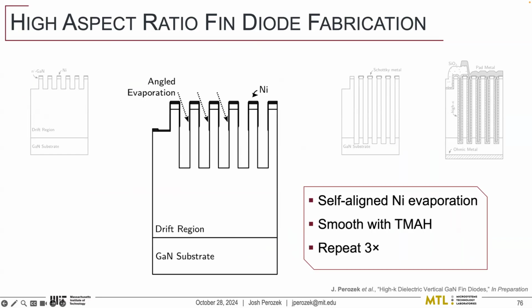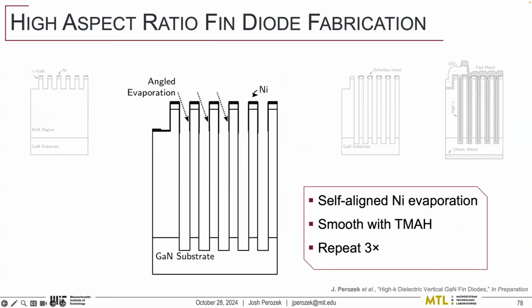So we remove the mask from the first one, we put on another one, etch it deeper, we clean it up with TMAH. We remove the mask again, we etch it deeper, clean it with TMAH, and then strip the mask. We do it one more time for a total of 3 times or 4 total etches. And we're able to make very deep, high aspect ratio fins here.